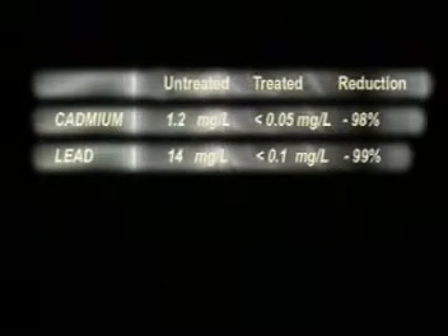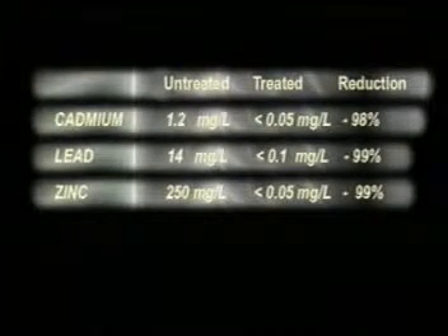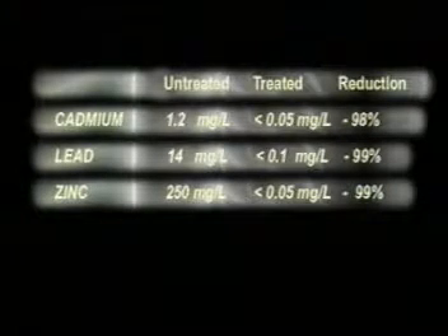Prior to stabilization, lead was measured at 14 milligrams per liter. Post-stabilization levels were less than 0.1 milligram per liter. A 99% reduction of leachable lead was achieved. Prior to stabilization, zinc was measured at 250 milligrams per liter. Post-stabilization levels were less than 0.05 milligrams per liter. A 99% reduction of leachable zinc was achieved.